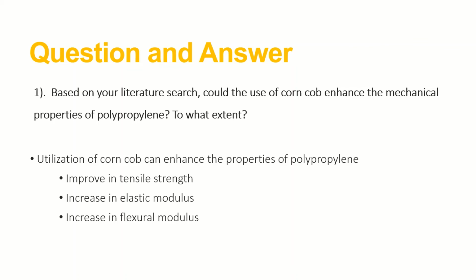Increase in elastic modulus was also observed in the studies by Salma et al. in 2014 and Ramos et al. in 2019. The increase in modulus of elasticity may be caused by the stiffness of the woody ring of the corncob. Hence, improvement in rigidity of the obtained corncob polypropylene composite. Lastly, flexural modulus was found to increase with the incorporation of corncob filler as mentioned by Juan et al. in 2017 and by Ramos et al. in 2019, which then again is associated to the stiffness of the corncob.